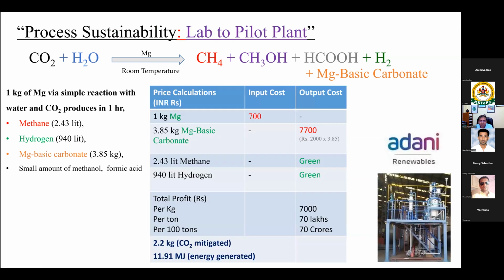Another very interesting thing we observed is that you don't really need magnesium nanoparticles in this process, you can use bulk magnesium. In fact, we went one step further and asked, can I use magnesium scrap, the waste lying around? We purchased some scrap from a supplier at 700 rupees a kg, converted that into a bulk powder, not nano, just a powder. The reaction still works, at a slightly slower rate, but still at room temperature, so the energy input is not required.